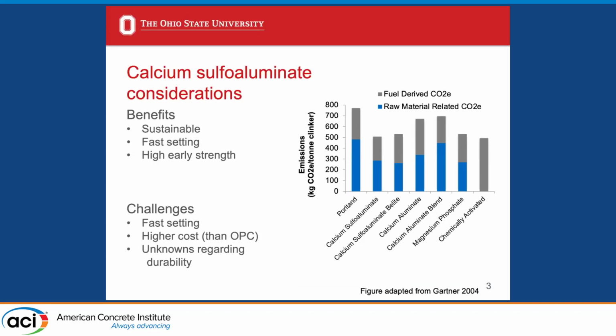I've shown here some data adapted from Gartner 2004, where he showed that you can obtain as much as a 45% reduction in associated embodied CO2 with calcium sulfoaluminate and belitic calcium sulfoaluminate materials when used in a 1-to-1 ratio. But in addition to that sustainability, calcium sulfoaluminate cements have a lot of benefits. Most predominantly, they're extremely fast setting.